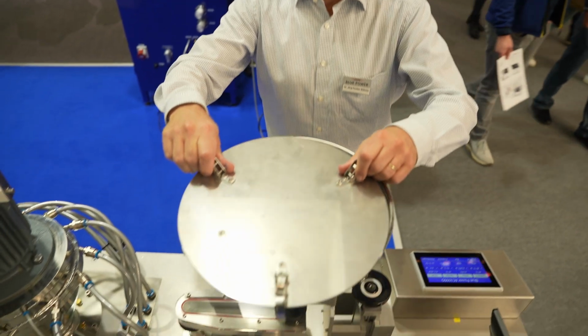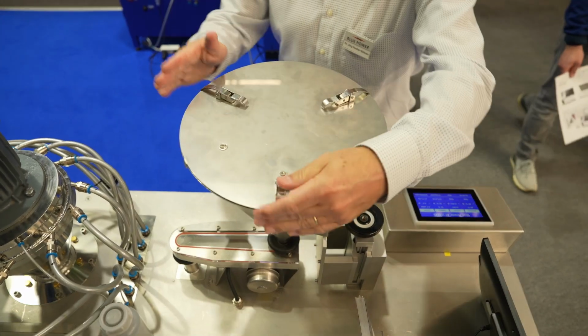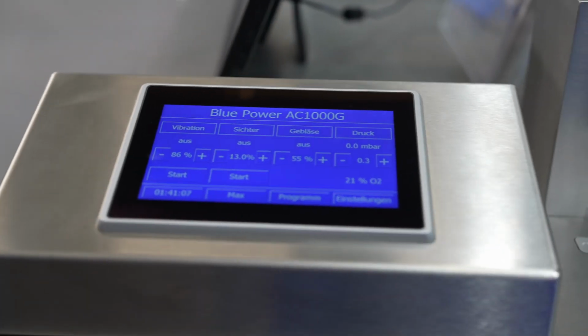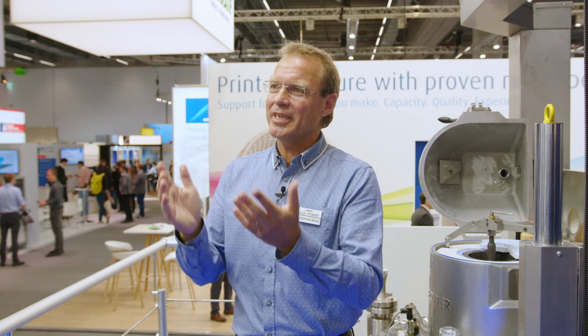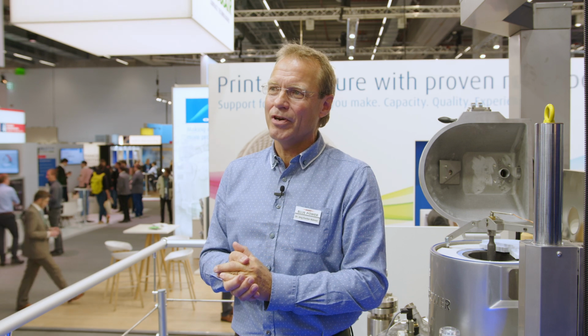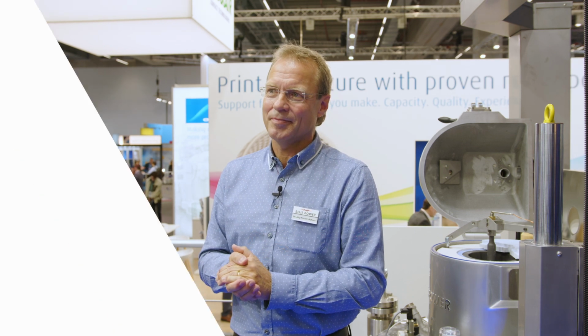So different to a sieving process where you work with discrete meshes, in this air classification process, you have the opportunity to continuously shift the cut point from basically 3 micron up to 100 micron or above. So that's a very convenient tool to fine-tune the properties and the fraction of the powder that you are going to use in the printing process.